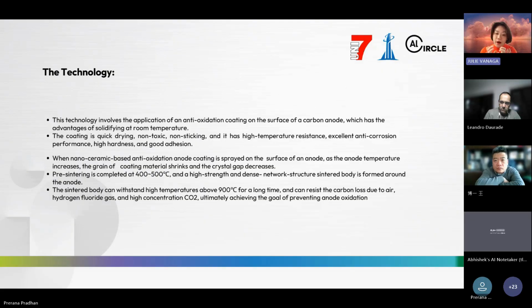a protective layer around the carbon anode, like a hard armor custom made for the anode. This armor is incredibly durable. It can withstand high temperatures above 900 degrees for a long time. It acts like an impenetrable barrier between the carbon anode and the oxidizing substances in the pot, including air, hydrogen fluoride gas, and high concentration CO2. By blocking this contact, the coating fundamentally prevents anode oxidation and carbon loss.